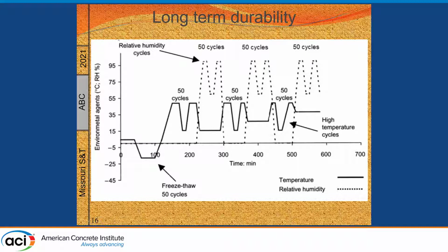This includes 50 cycles of different temperatures, moving from hot to cold and vice versa. We have another 3 times 50 cycles of different relative humidities, and also another 50 cycles of freeze and thaw. Typically we start with 50 cycles of freeze and thaw, then 3 times 50 cycles of temperature, and then 3 times 50 cycles with relative humidity. This was a very aggressive environmental condition, developed a while ago by Dr. Nanni to summarize severe weather here in the Midwest.